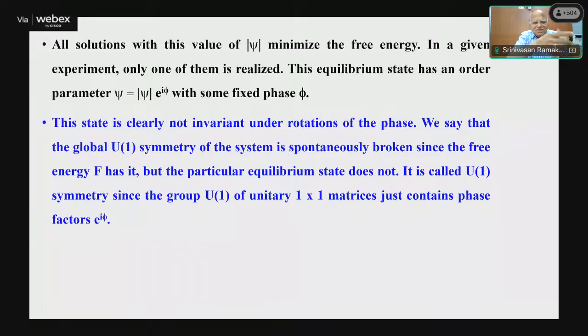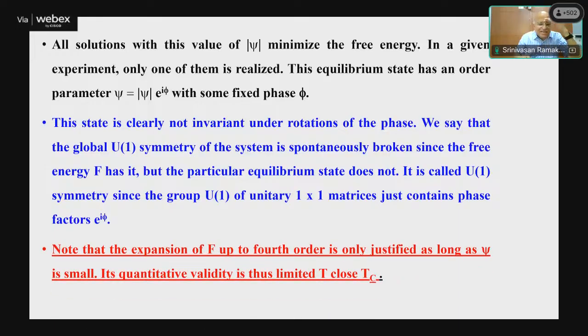So we say that the global U1 symmetry of the system is spontaneously broken, since the free energy has it, but the particular equilibrium state, the superconducting state, doesn't. It has only a fixed value of phi, unlike all values of phi taken in the normal state. This is called the U1 symmetry being broken, because U1 symmetry requires phi to take all values. So this symmetry is broken in the superconducting state. That is how the order parameter is described. Note that the expansion to fourth order is justified because psi is small. That is the reason why we are working close to Tc. The value of psi is small.